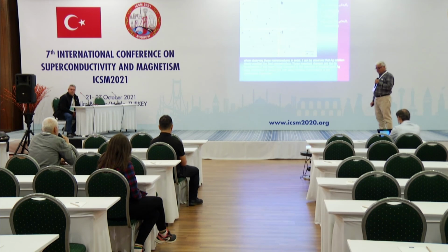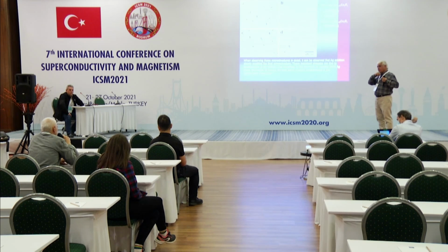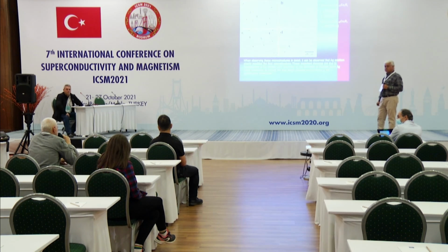And did you have any, this is the second question, did you observe any copper alloying with silver? Because when you have copper atoms in the matrix at high temperature, they tend to alloy with silver. Did you observe such a phenomenon? No, we have not observed such a kind of phase. Okay, I did some experiments on this issue some years ago. A couple of microns layer is influenced by the copper migration. You get some sort of silver copper alloy when you heat treat the sample at high temperature. That may slightly change the local copper content of the sample, the copper stoichiometry of the sample. Anyway, thank you. Thanks.